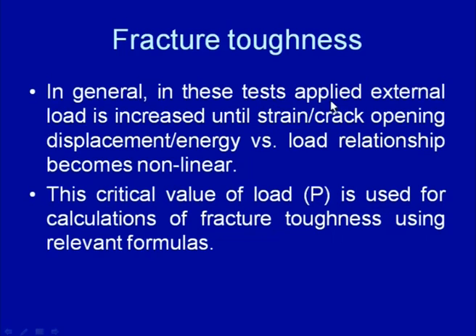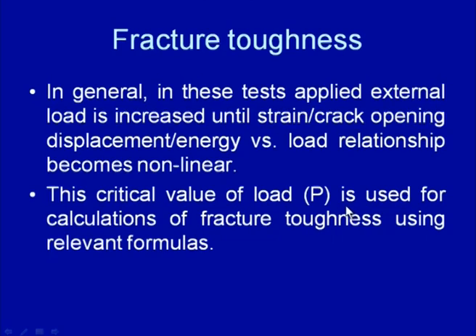In general, for conducting these tests, external load is applied and it is increased until the strain, or the crack opening displacement, or the energy versus the load relationship becomes non-linear. That critical value of the load where it deviates from linearity is used for calculation of the fracture toughness using the relevant formulas.